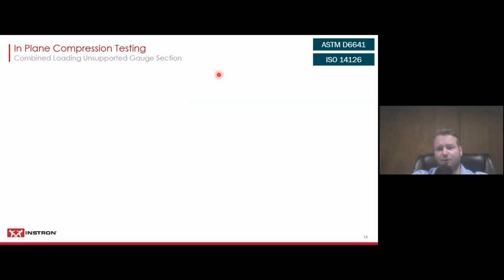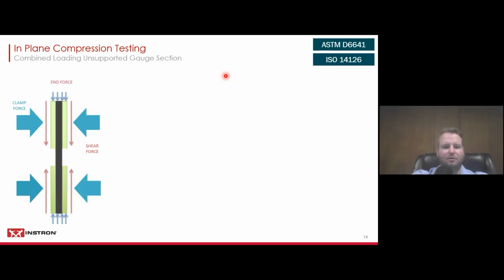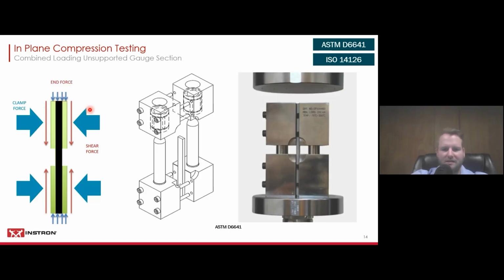And now moving on to what I would consider the most common, most popular in-plane compression test, which is the combined loading approach. So we're using both of those techniques that we saw on the previous slides. And by far the most common standard for that is ASTM D6641. And in the most recent revision of ISO 14126, it does allow this fixture, cutting out the end loading and now allowing shear or combined loading in compression. And that would look kind of like this. You can use either tabbed or untabbed specimens, and then you have a clamping force from the sides onto your specimen, and at the same time also some end loading. So you're initiating the load with both techniques at the same time. And this is how that fixture looks.